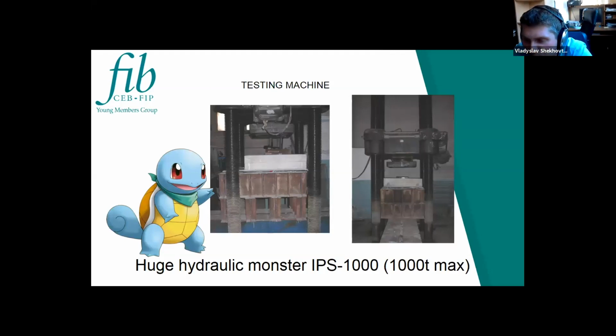Yes, here is the testing machine. It is a monster because it can give pressure of 1,000 tons. We used such power of this testing machine when testing the anchors of the plates which hold the reactor zone of an atomic nuclear station. These anchors were tested on this machine, and the failure load was near 950 tons, if I am not mistaken. So I saw that this machine was working at the best of its opportunity.